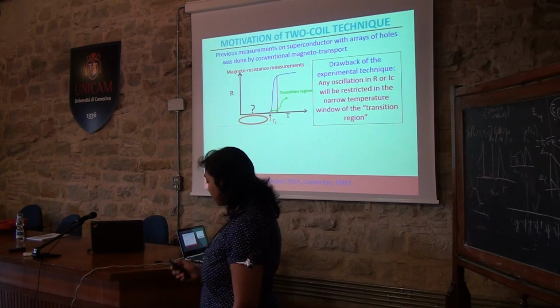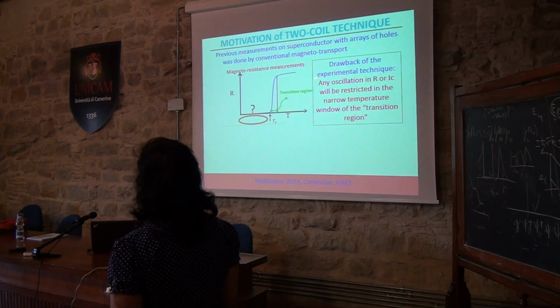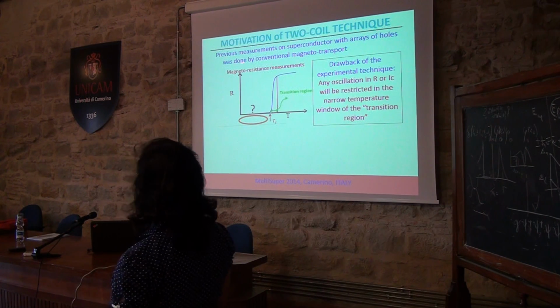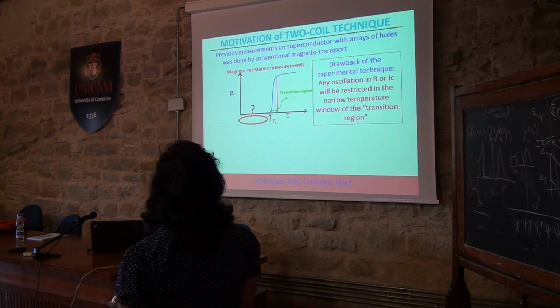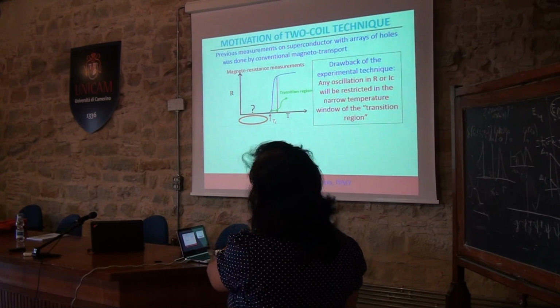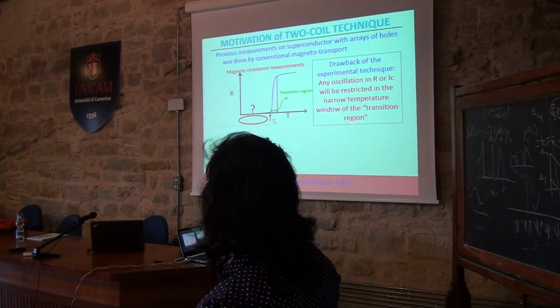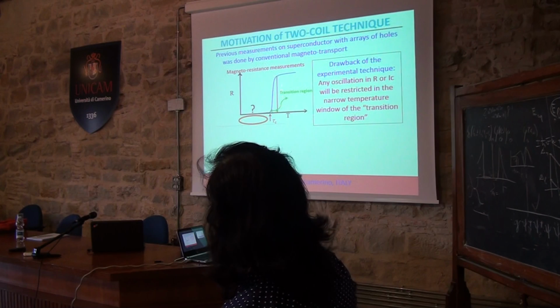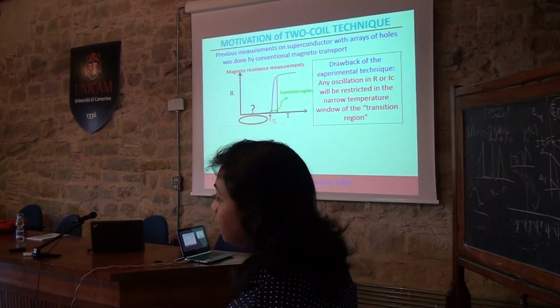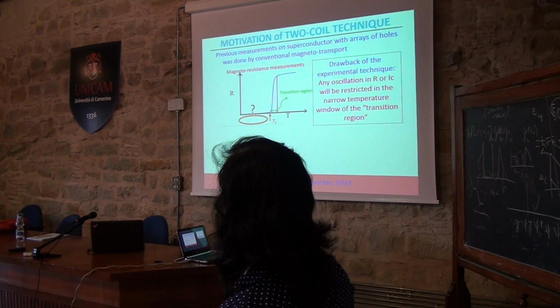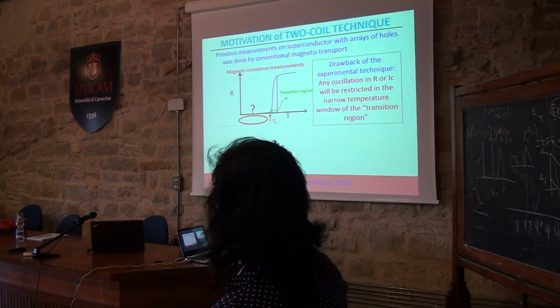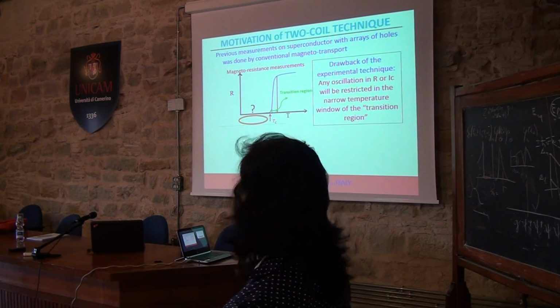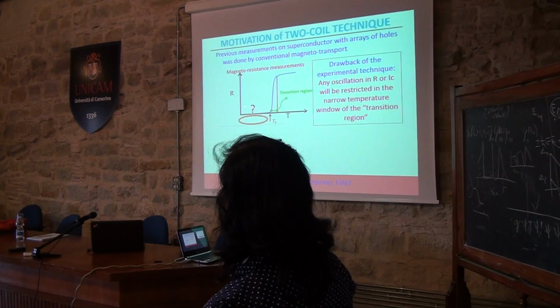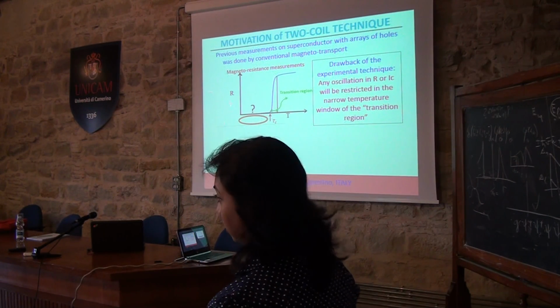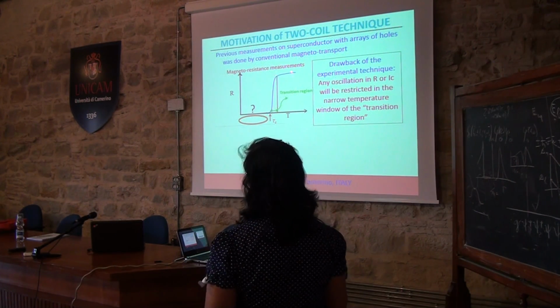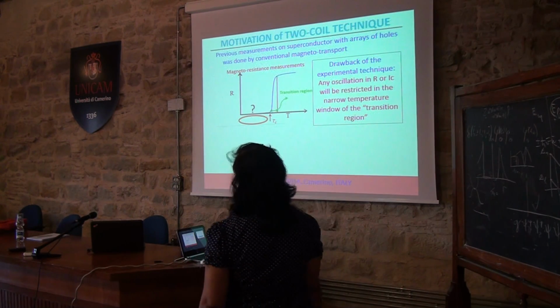As I said, most earlier experiments were done by transport measurements. One limitation of transport measurements was that when you study matching effects, you are restricted only to this transition region, because that's where you have signal and you want to see an oscillation over this signal. So you don't know what is happening deep in the superconducting state. Most measurements were confined very close to the transition temperature.